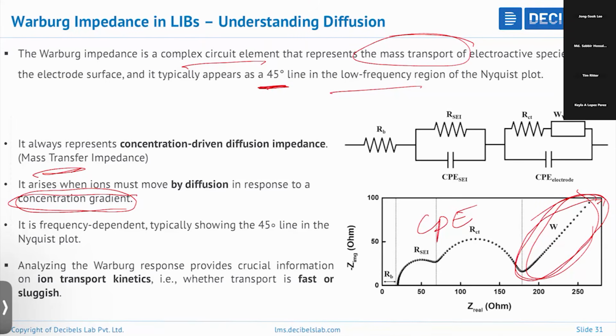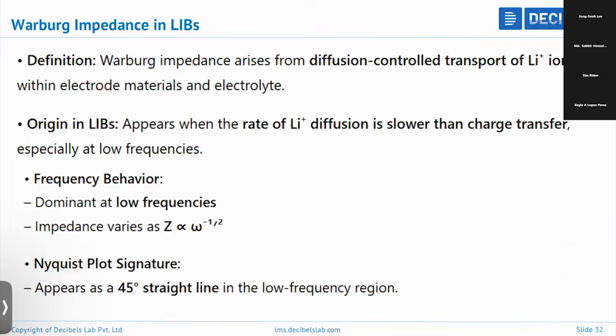So it's frequency dependent, typically showing the 45 degree line in the Nyquist plot. So analyzing the Warburg response provides crucial information in ion transport kinetics, whether the transport is fast or sluggish. So it appears when the rate of lithium ion diffusion is slower than the charge transfer, especially at low frequencies. So it is dominant at low frequencies.